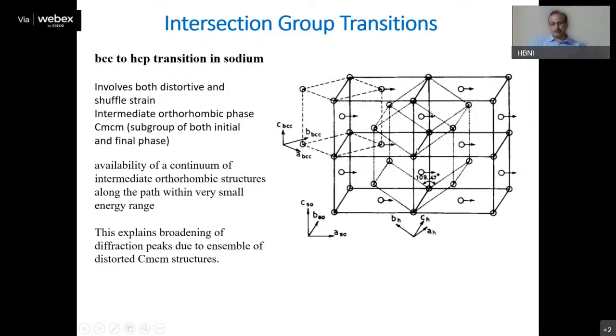transition. So what you need to do is, some of the atoms have to move in this direction, and then this angle changes. Basically the axis has to be suppressed such that this angle becomes 120 degrees. When it becomes 120 degrees and these atoms move by some amount, then you get this phase transition from BCC to HCP. Now again in this case, the intermediate phase should be an orthorhombic phase.